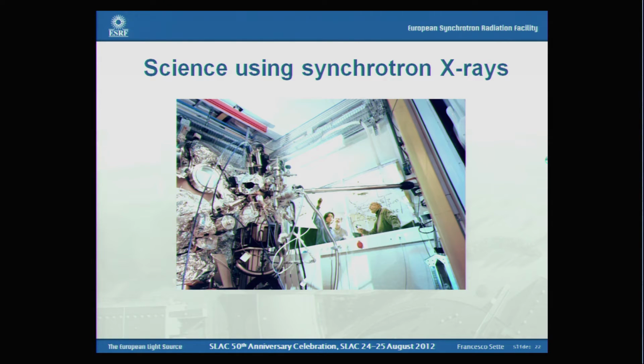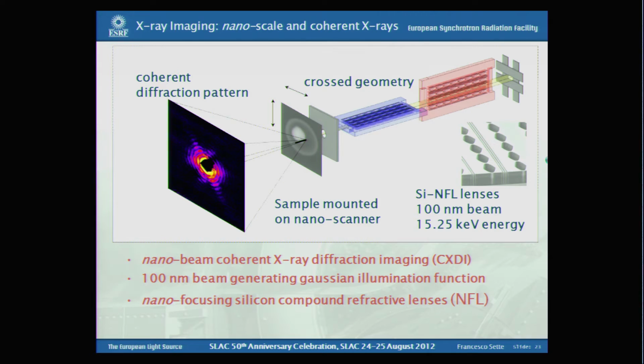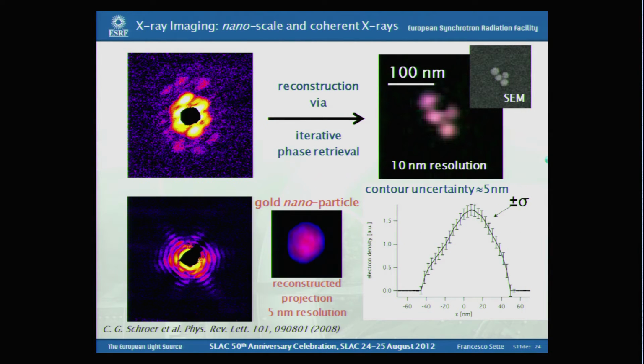So let me now switch for a moment to the science. This brighter beam, for example, has now allowed us to start to use coherence also in the X-ray regime. Very quickly, by having a small opening, you can select the coherent flux and illuminate your sample, and you look at the diffraction of your sample, and by techniques of reconstruction by iterative phase retrieval, oversampling, and so on. And we'll hear much more later today on the application of X-FEL. This is a very interesting technique that could allow us to have resolutions of the order of 5 nanometers. This has been obtained in very favorable conditions on gold particles, but you can see here that it's really at the limit of the statistics, and this is just because we are flux limited at this stage. So there is a real need for even brighter beams.